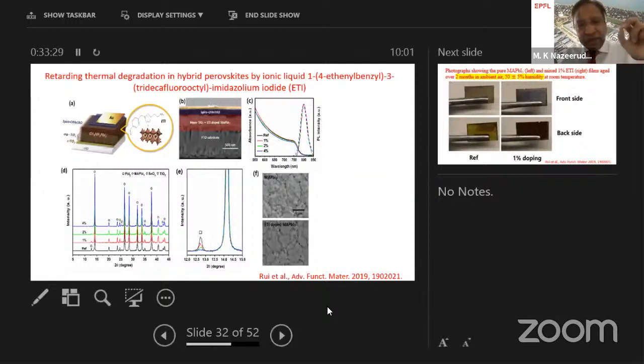People who are working in perovskite solar cells understand there are issues with the perovskite materials. That's called hysteresis. So this hysteresis is due to three reasons. One is imbalanced charge extraction. Second is ion migration. So this ion migration is because these perovskite materials are ionic compounds. So can we increase the ionic composition by doping the perovskite with ionic liquid?